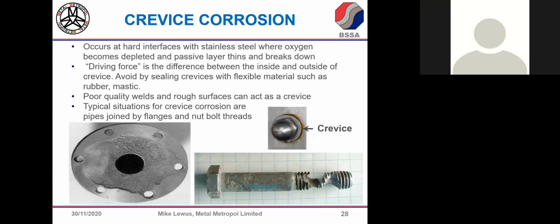If you add chloride in there, you very quickly end up with an environment where oxygen can't readily diffuse to the stainless surface, so the passive layer breaks down. Add in chloride, that accelerates the whole process, and it doesn't usually take long before some level of corrosion occurs.